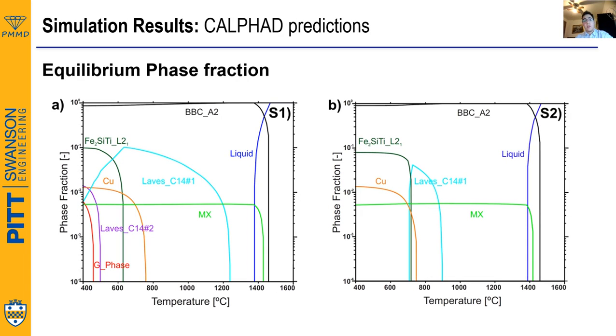Now, in order to remove this segregation and have a more uniform microstructure, a homogenization heat treatment needs to be carried out. In order to select the homogenization temperature, we again rely on CALPHAD. Based on these phase fraction predictions and the limits of our lab furnace, we set the temperature for the homogenization to be 1200 degrees C.